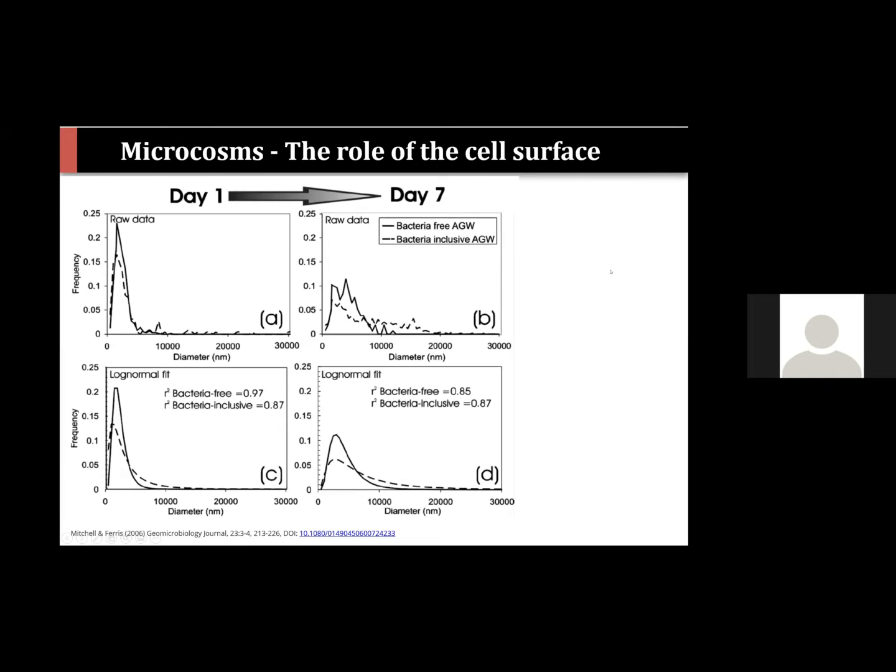And we generally see that the mineralogy and general morphology of the calcium carbonate precipitates is the same in both zones of the reaction. So it kind of seems that the presence of cells doesn't actually affect the mineralogy or general morphology.